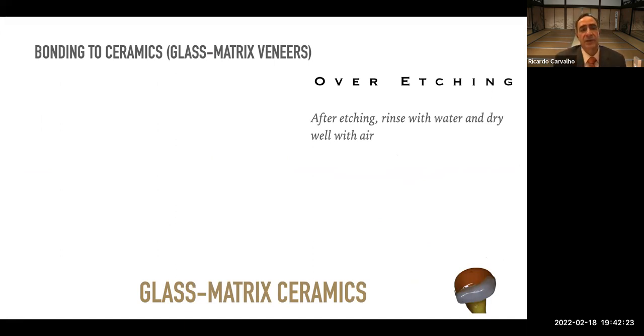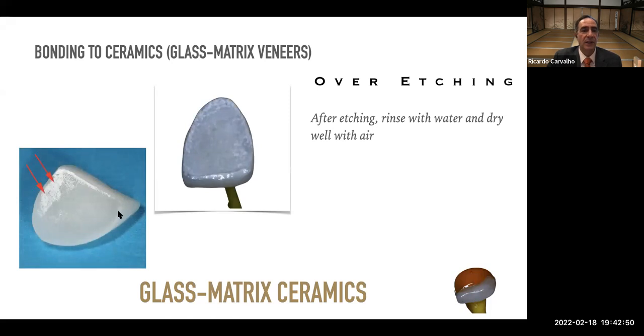And that is really important to realize and be able to recognize over-etching phenomena clinically, because overetching will actually deposit some residues, a residue of salt formation on the surface that might compromise your bond. So it's really important that after etching, you rinse well with water and you dry well with air. And then you look at the surface of your veneer, for example, and if you see these whitish areas, sometimes all over the surface, that is the clinical indication that those particular areas were probably overetched.